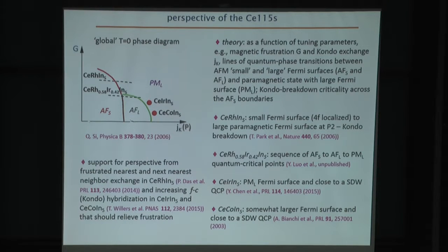So from this body of information, as well as the known evidence for magnetic frustration in cerium rhodium indium 5 and the known increase in conduction electron-f electron hybridization in the sequence cerium rhodium indium 5, to iridium-doped, to cerium iridium indium 5, to cerium cobalt indium 5, it seems now that we can with some confidence place these materials on this so-called global quantum phase diagram, with cerium rhodium indium 5 here, this iridium-doped cerium rhodium indium 5 material here, cerium iridium indium 5 and cerium cobalt indium 5. In all of these cases, crossing these boundaries has associated with it the development of d-wave superconductivity.